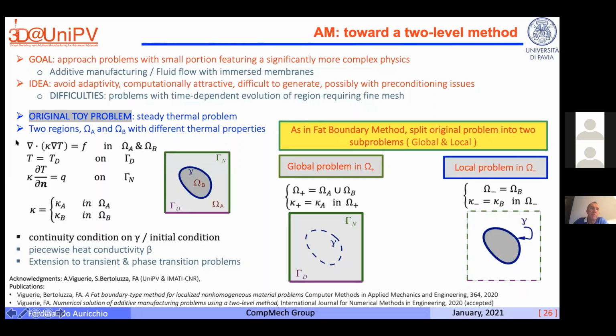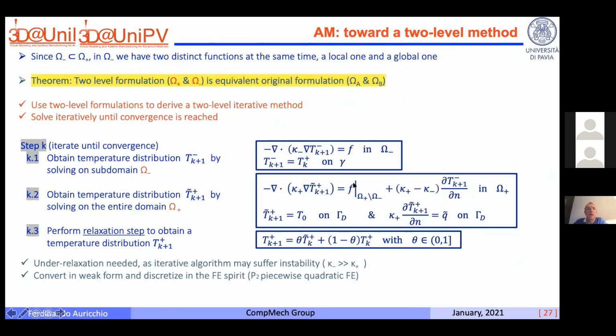For example, take a very simple toy problem, let's say just a thermal problem. If you have a thermal problem in a certain domain, for example with an inclusion, you split your thermal problem into a global problem which does not see the inclusion, and a local problem which sees the inclusion. So instead of solving the problem in domain A and domain B, taking into account the different properties of the two regions, you solve the problem in a global domain and then in a local domain. And you can develop numerical tools where you solve first the problem locally, then globally, and then you iterate between global and local, and you get convergence to the right solution.